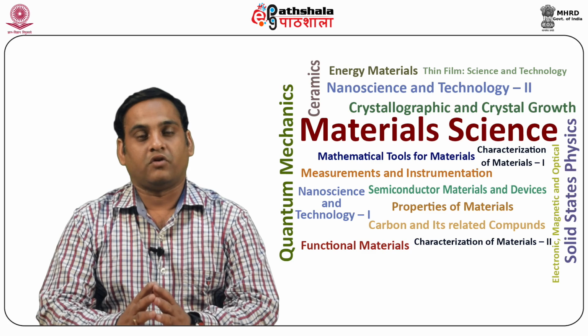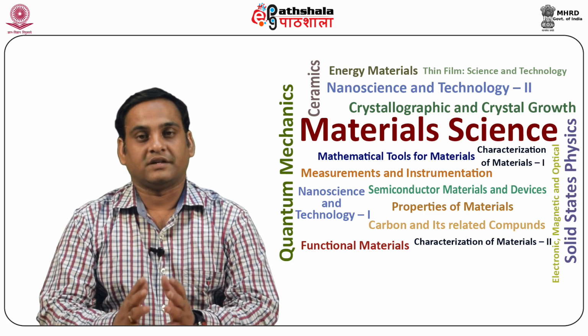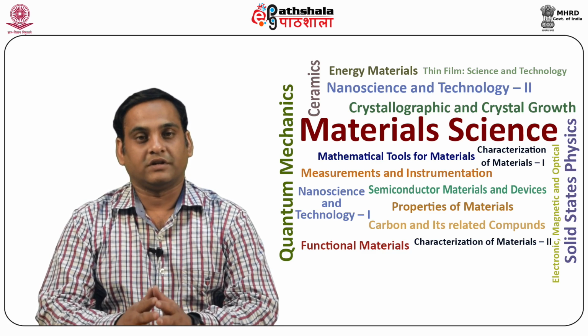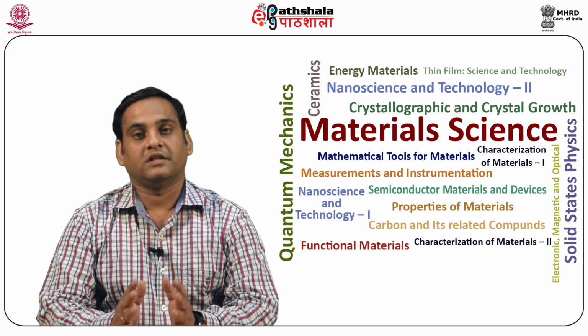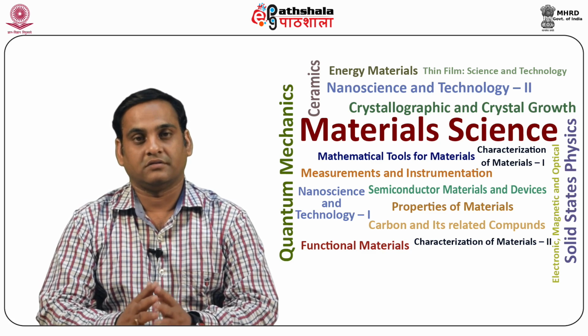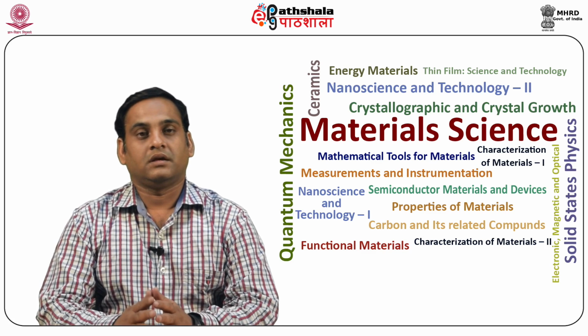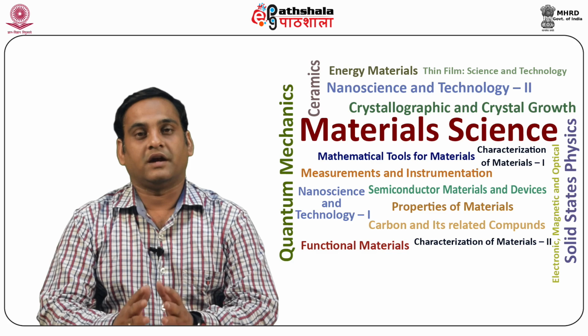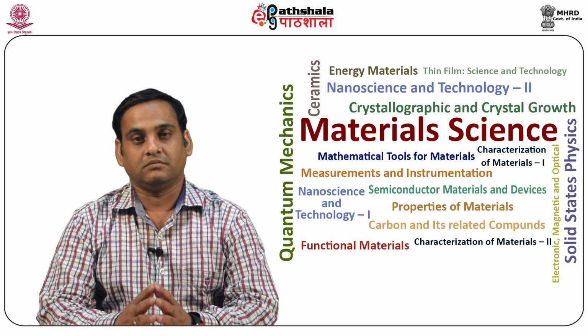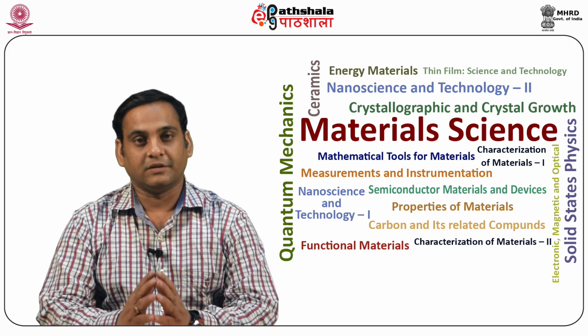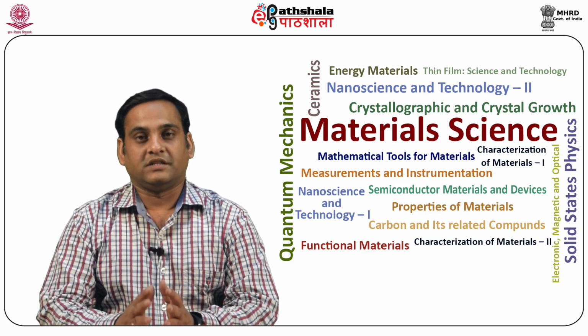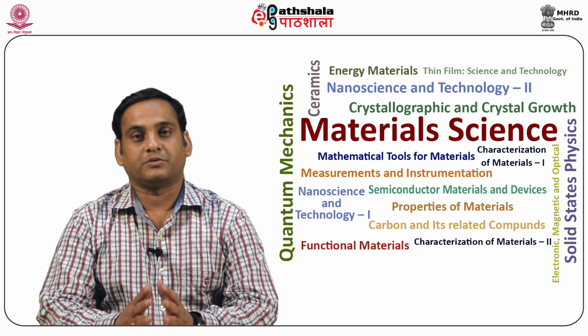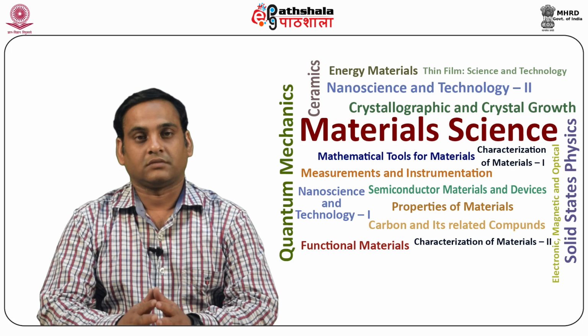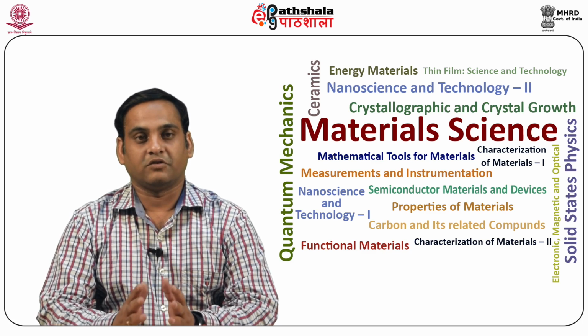The oxygen ions form an octahedron at the center of which the titanium ion Ti4+ is located. The Ti4+ is considerably smaller than the space which is available inside the oxygen octahedron. It thus has a high ionic polarizability for two reasons. One, it has a charge of 4 electrons, and it can be displaced over a relatively large distance. We shall see that this may be the explanation for the occurrence of spontaneous polarization in BaTiO3. There is an intimate relationship between the ferroelectric properties and the atomic arrangement in ferroelectric materials.